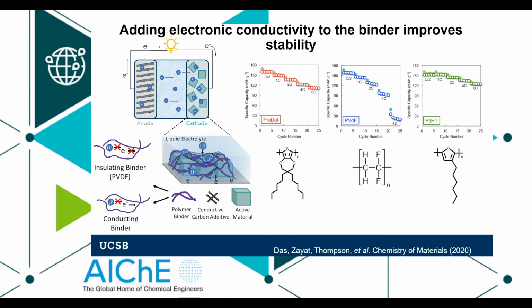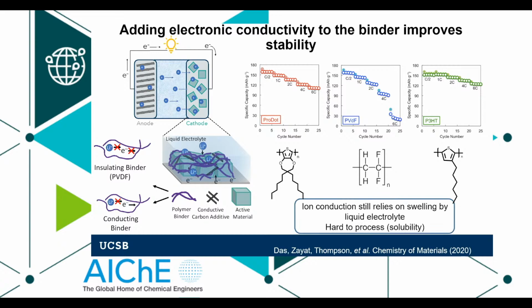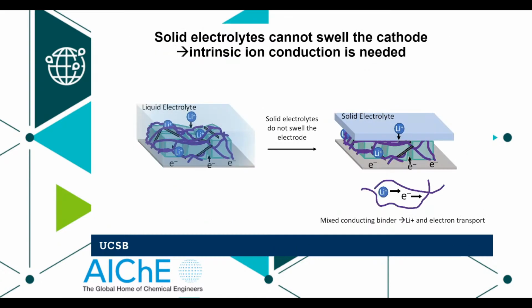The other big problem with making that one-for-one replacement is that conjugated polymers aren't very soluble. And so in order to process this thing, we have to jump through a lot of hoops to get a very insoluble polymer to actually work here. So this ion conductivity is a problem, and they're really, really hard to process. But what makes matters even worse is that if we move to solid electrolytes, now we have a real problem with ion conduction. When we were dealing with liquids, the liquid electrolyte could kind of swell our glue and make it work. If you have a solid electrolyte, you're not going to be able to swell your glue, and that lack of ion conduction will become fatal to the overall device.